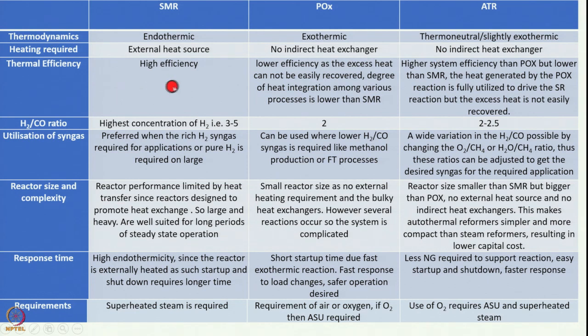The thermal efficiency with the use of several heat exchangers is higher in the case of steam methane reforming, but in partial oxidation there are exothermic reactions occurring and it is very difficult to recover the excess heat obtained in the process. So, the degree of heat integration among the various processes is not like it was in the case of steam methane reforming. In autothermal reforming, the system efficiency is comparatively higher than partial oxidation, because the heat produced is utilized by the reaction within the reactor. But at the same time, the reaction heat cannot be completely recovered. So, the excess heat being produced cannot be recovered in the process.